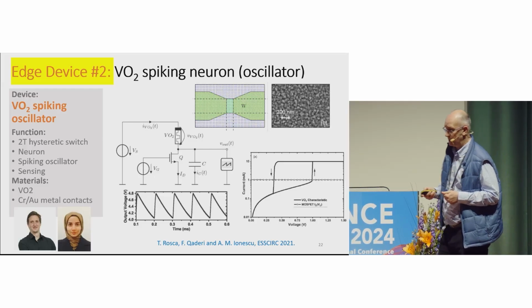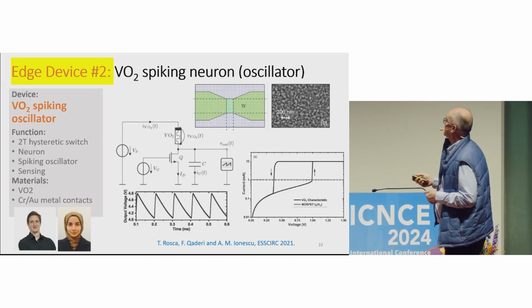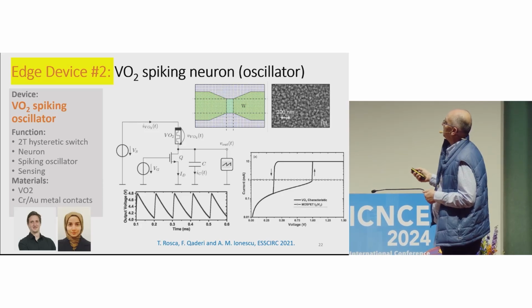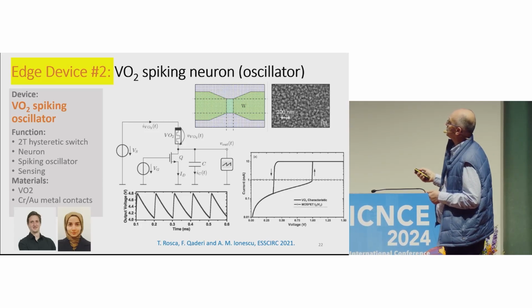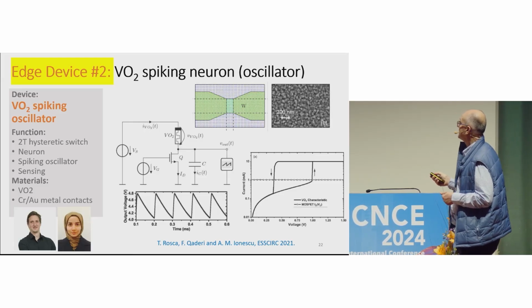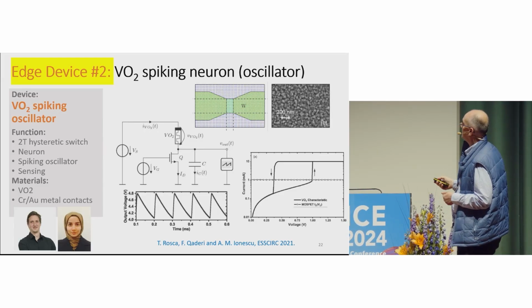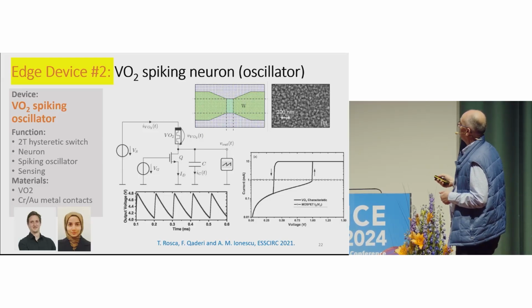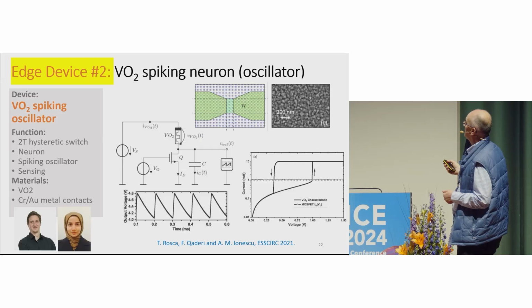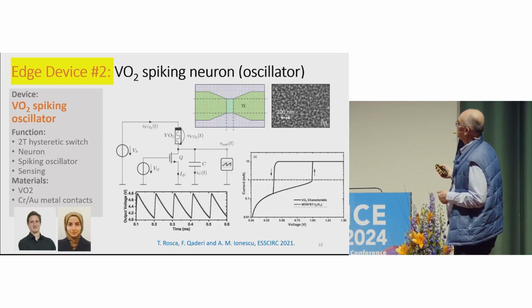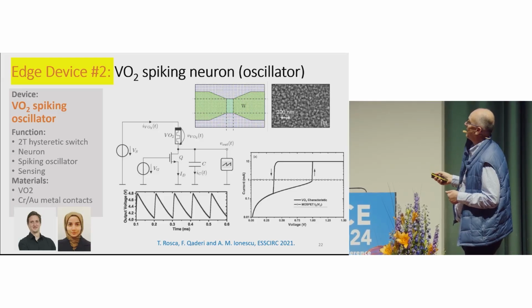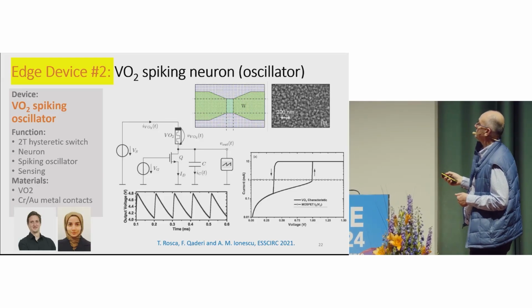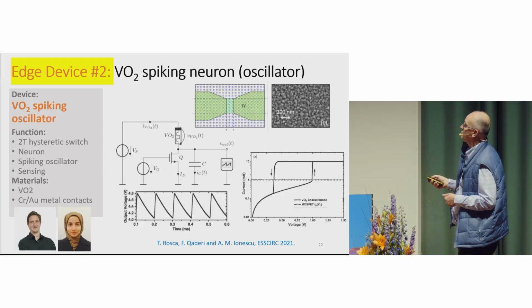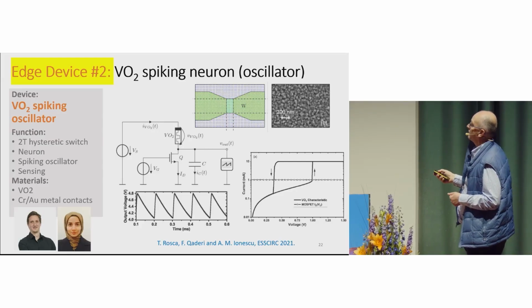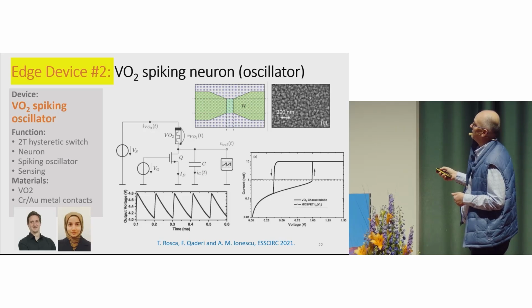And what we have done here is something, again, extremely simple. In reality, we try to have such a resistive switch that switches electrically from a resistive state that is very high. Here, this is the current, and this is the voltage on this VO2. So you can switch it up with a voltage of 1 volt, and then it switches down between 0 and 1 volt. And then we practically bias it with a MOS transistor that is in saturation. So we choose the bias so that this is in saturation. Now the voltage on this transistor is the supply voltage minus the voltage on the VO2. So you have to put the saturation curve oppositely.